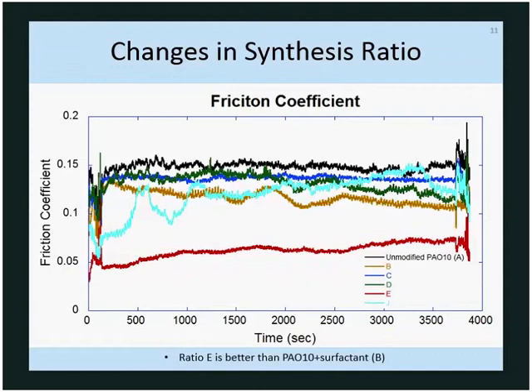And in changing the synthesis ratio, you can see that we actually found an oil that had one of the ratios exhibited very low friction, which is unseen for a lot of polyoxometalate lubricant additives today. And that was seen at a steady friction coefficient of around 0.05 throughout the duration of the 1 hour test. And then this is just changes in synthesis ratio.